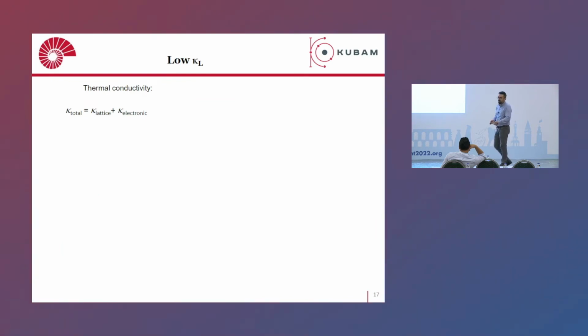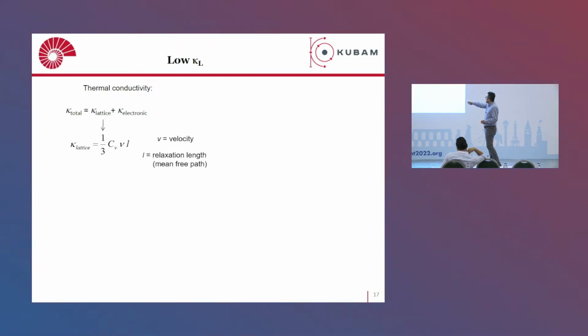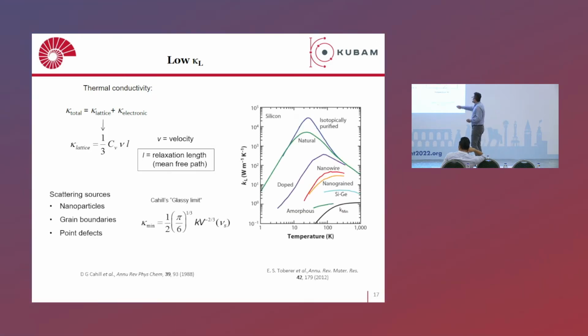Now, what about the thermal conductivity? So for thermal conductivity, I told you that the electronic part is connected to the electronic structure through the Wiedemann-Franz law. So the lattice one, you can see here, the lattice thermal conductivity, is dependent on the specific heat times the phonon velocity and the phonon mean free path. So you can lower this relaxation length or the phonon mean free path by introducing different scattering sources into the microstructure by nanoparticles, by introducing large density of grain boundaries, and also some point defects.